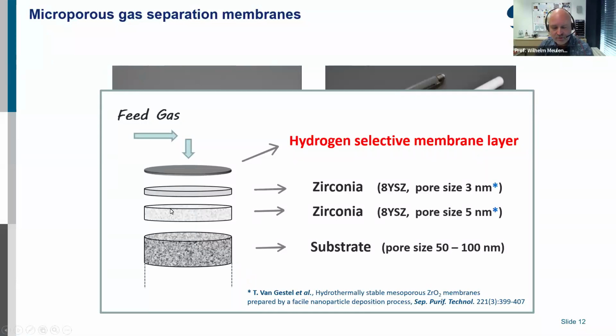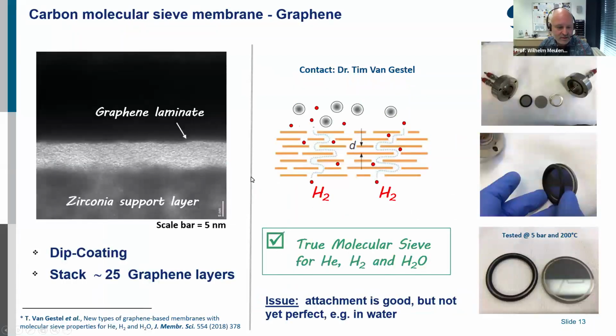So the question is now, when we want to separate gases, we have to add these hydrogen selective membrane layers. What I already showed can be a silica or a graphene. But one problem of these existing graphene layers is that they stick very well to the support, but sometimes after application, you can see here, it was tested at 5 bar and 200 degrees C, and then if you remove the polymeric sealing from the membrane, you have a delamination on the edges, especially when water is in the atmosphere. That means the attachment of the membrane to the support layers and the intermediate layers is good, but not good enough, especially in water.